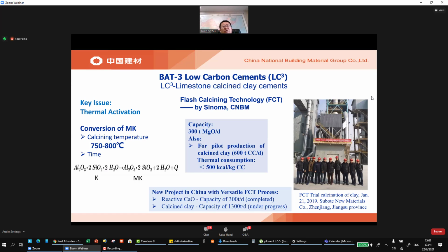The research actually is also a review that 40% of the kaolinite content in the raw clay is good enough for producing good quality, very low clinker factor, low carbon cement. Certainly, the higher the content of kaolinite, the better its performance, and the larger the replacement of clinker for the production of low carbon cement.